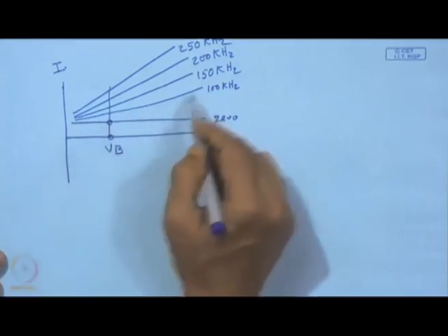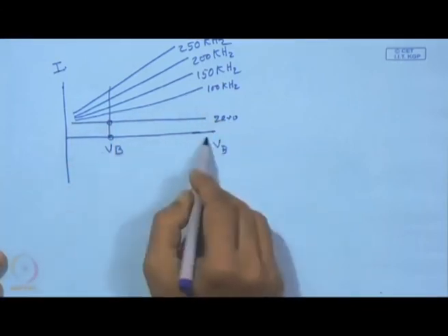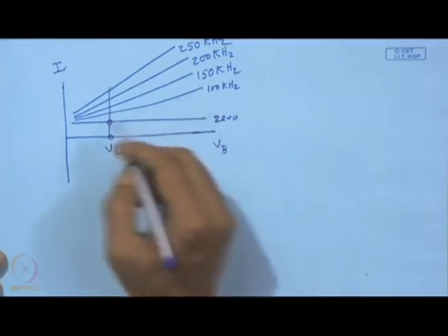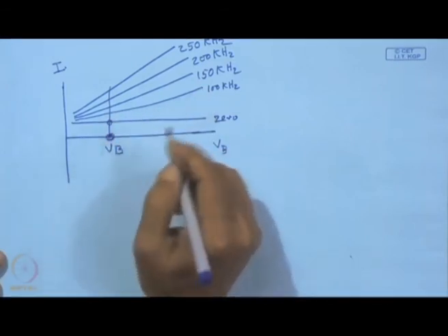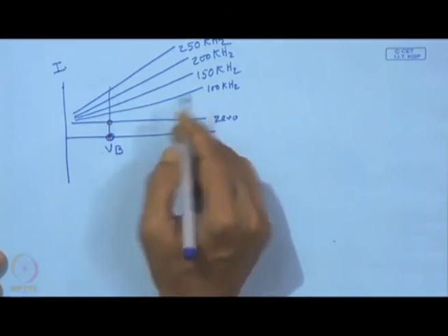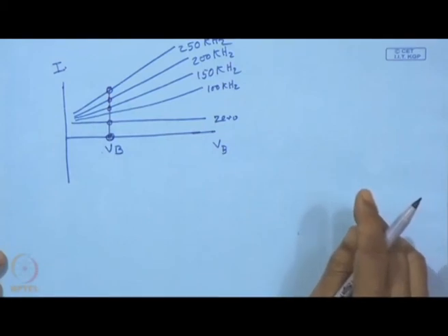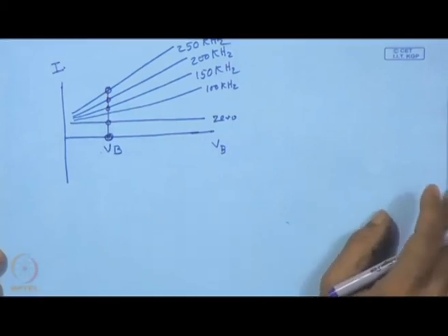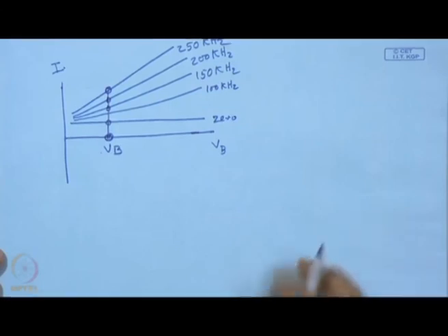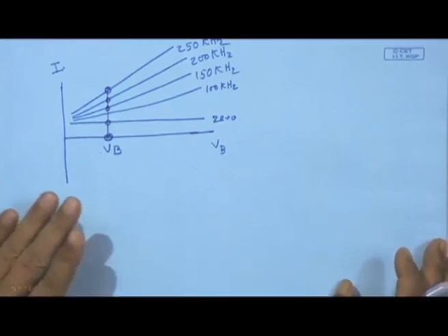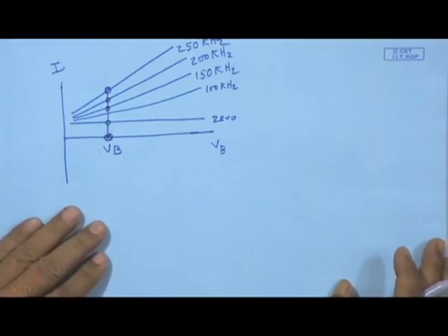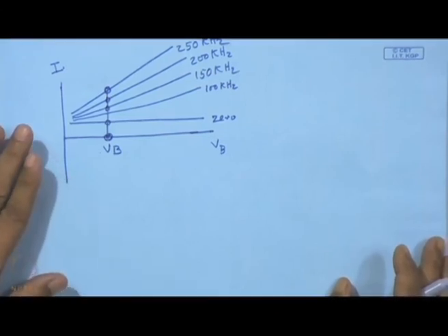But what we can see now, since it is under pulsation, is that with voltage it will also increase, but again at the same low voltage, if we keep on changing the frequency, we can also get the substrate current at an enhanced rate, and that is very advantageous. The whole idea here is that with a low biasing, we must have proper enhancement of ion current.